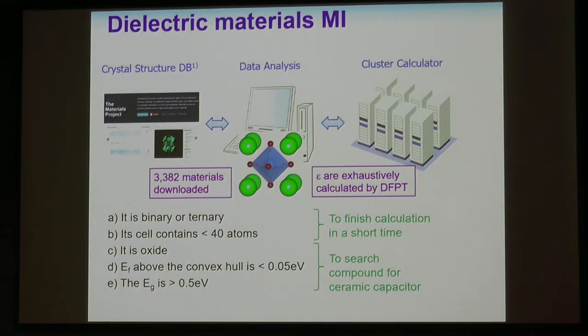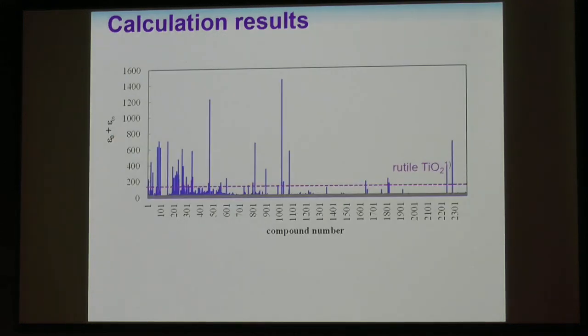Then we constructed this kind of materials informatics process. We can choose candidate materials from the Materials Project database using these criteria. It's something like oxide, insulator, and easy to synthesize, something like this. Then we can calculate the dielectric constant by the DFPT method. Then we search for high dielectric constant materials. One of the results is shown here. This is only for the material numbers. We cannot name names, but some materials have very, very high dielectric constants, exceeding 100.